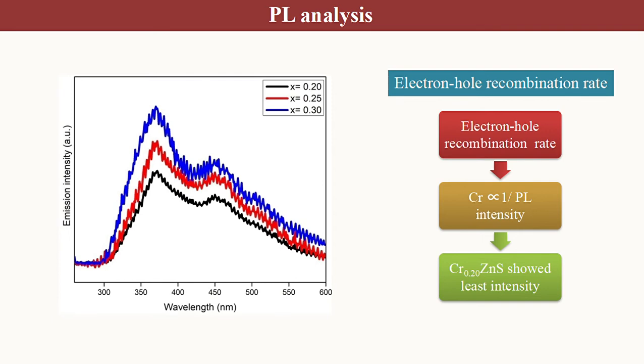The catalysts were further characterized with the PL technique to determine the extent of the photo-induced electron-hole recombination rate. Principally, high PL emission intensity represents the rapid recombination of charge carriers. The figure shows the PL emission spectra of the chromium-doped zinc sulfide catalysts measured at room temperature and an excitation wavelength of 325 nanometer.